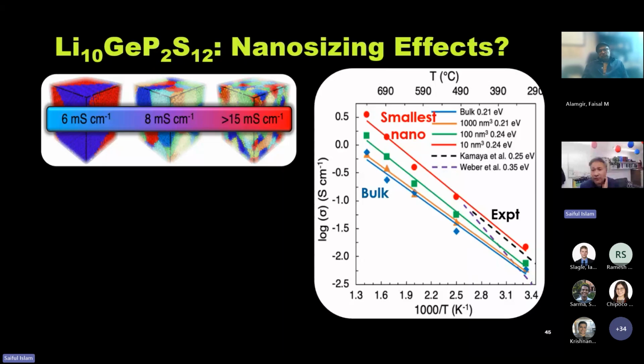This is Arrhenius plots of different size materials. In blue is the bulk, and in red is the smallest nanoscale, as small as about 10 nanometers. And you can see the experimental data in black. So what am I trying to show? Well, first of all, there's reasonable accord, not perfect, but reasonable accord with experimental data, although the two experimental plots don't agree with each other, but we are in quantitative accord.